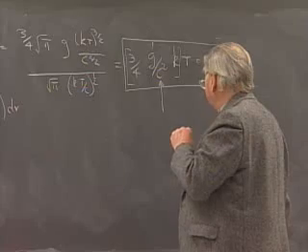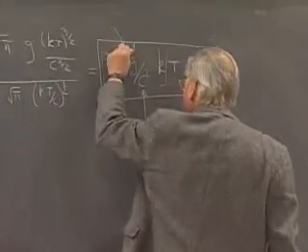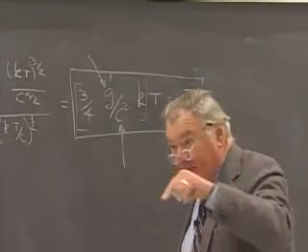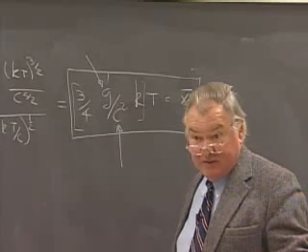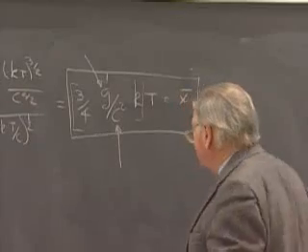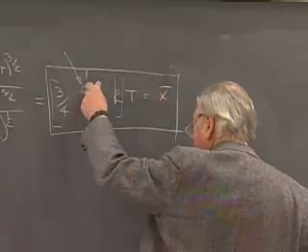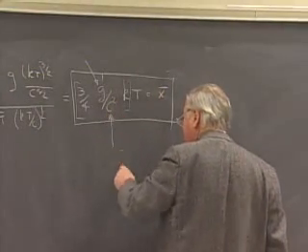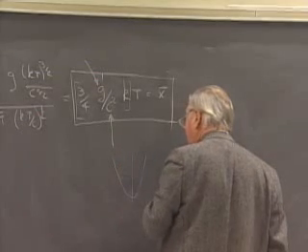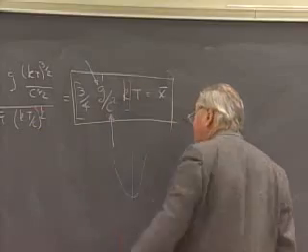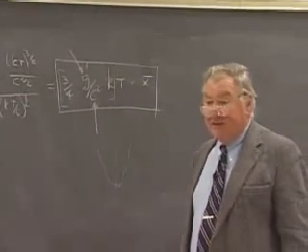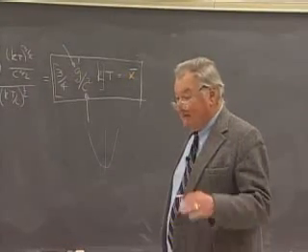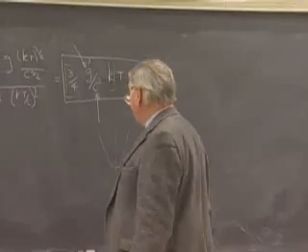And then finally, the last important term to survive is g, the asymmetry. The thermal expansion coefficient should increase with the first power of the term that describes the asymmetry of the potential well. Okay. So your intuition would tell you that that's the way the linear thermal expansion coefficient should vary. The interesting thing is that it depends more strongly on the parameter that gives the parabolic part of the potential well. And secondly, that it does predict a separation that increases in proportion to temperature, and therefore there is a constant linear thermal expansion coefficient.